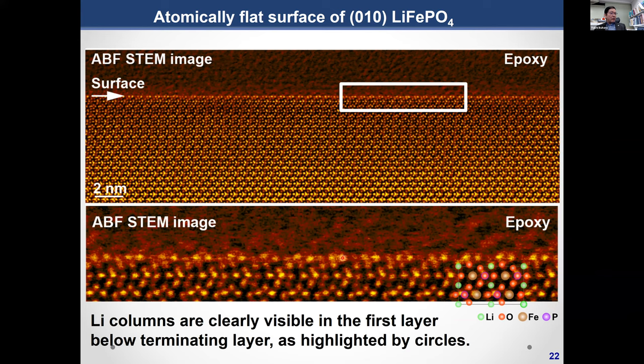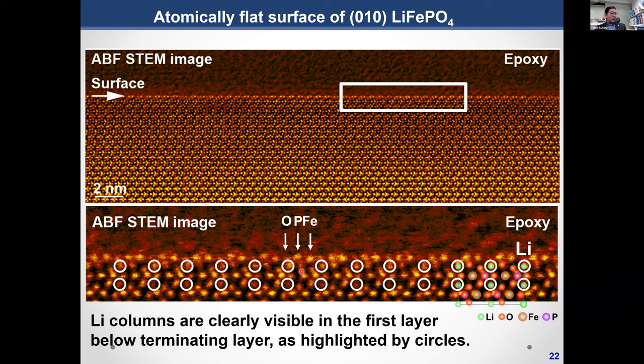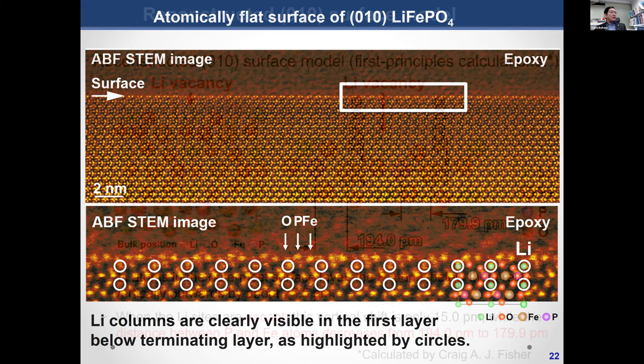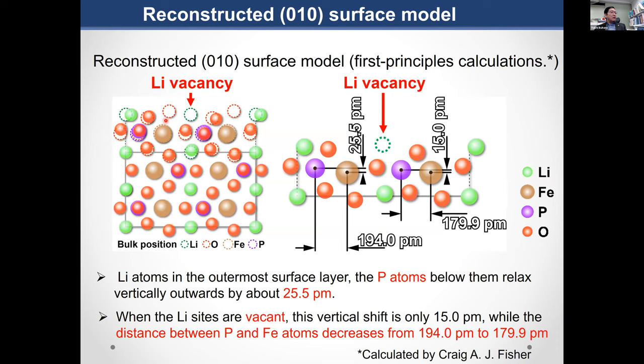We actually calculated the relaxation behavior by using first principle calculations. I will show it later. But you can see the oxygen column, and the phosphorus ion can be clearly seen on the outermost layers. In addition to this, you can see lithium double columns like that. You can see all atoms. And these are the results calculated for surface relaxed structures by first principle calculation. In this case, we used the VASP code.